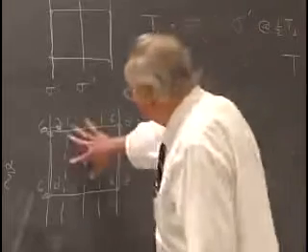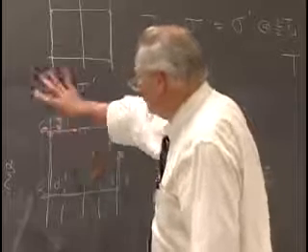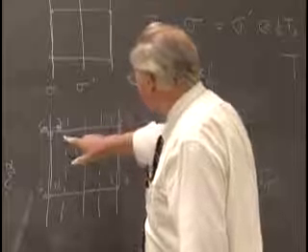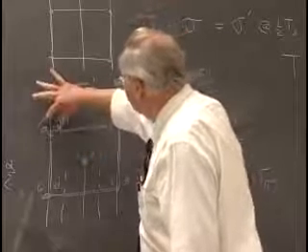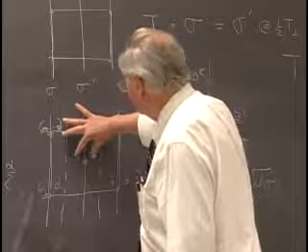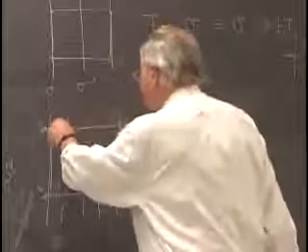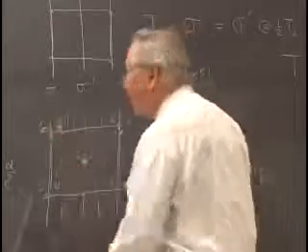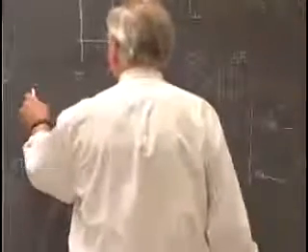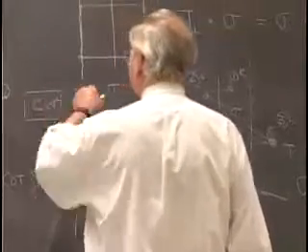So the glide plane, this new operation that popped up, does what the new operations did in all of the other preceding groups. It tells you how to get from the pair that you've hung at the lattice point to these that sit in the center of the cell. They're related by translation, but the relation of one to another of these motifs is by the glide plane. So that is an operation which has arisen in the group, and this then is a group that we would call CM, C for a centered rectangular net, as opposed to the primitive net, which is the one we got immediately before.